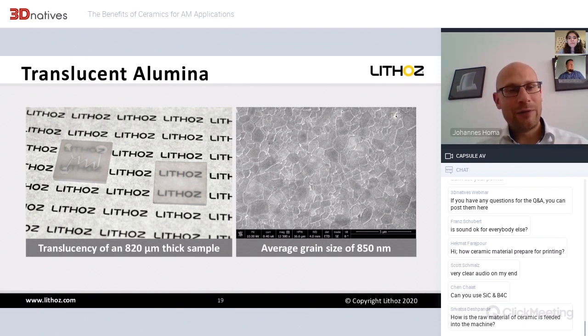Because if something is translucent, you cannot hide anything. You cannot hide cracks, you cannot hide voids or pores. And you really have to do everything correctly, starting from the powders up to doing the sintering. So if you want to check with one additive manufacturing process to see if they really can process ceramics, you just ask, can you show me a translucent alumina? And if not, you just know that they are not working on the edge of ceramic processing.